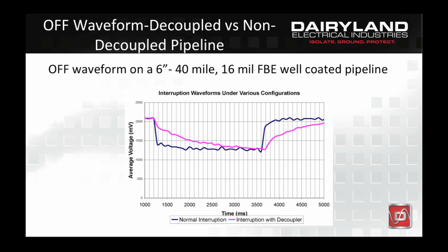The higher the resistance of the pipeline coating and the shorter and smaller the diameter of the pipeline, the higher the resistance to earth and the higher the R and the RC time constant. This is because there is less surface area of coating in contact with earth. Conversely, larger diameter and longer pipelines will have a lower resistance to earth due to more surface area of coating in contact with the earth and therefore a lower RC time constant for the same coating resistance.